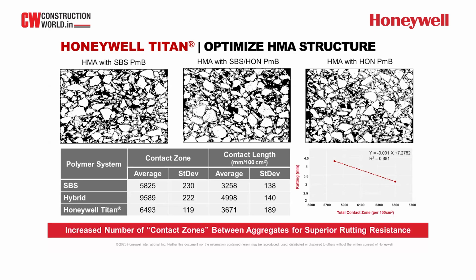The higher the total contact zone or contact number, the less the rutting, right? So R squared is 0.881, almost 90% R squared. So that tells us, if you have more stone-to-stone contact, which we call the contact zone or contact point, you have less rutting, so you will build a stronger road, with fewer failures and better durability.